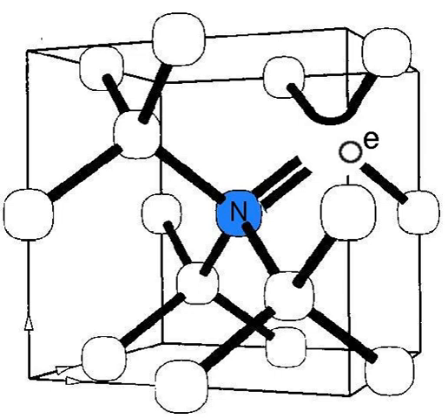The NV0 centers can be converted into NV- by changing the Fermi level position. This can be achieved by applying external voltage to a p-n junction made from doped diamond, e.g., in a Schottky diode. In the negative charge state NV-, an extra electron is located at the vacancy site, forming a spin S equals 1 pair with one of the vacancy electrons.